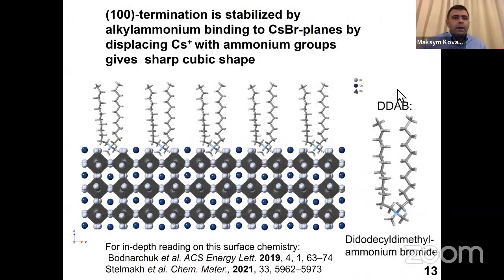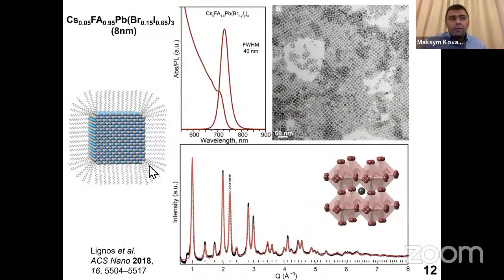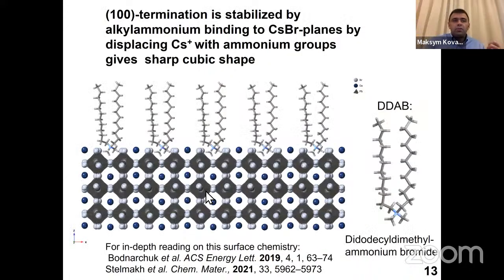So you may be wondering why they are always cubic shaped. That has something to do with the intrinsic crystal structure, because the perovskite lattice is derived from a cubic-like crystal structure, but it's also essential to consider which surface facets are stable.